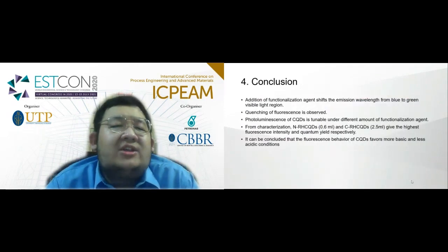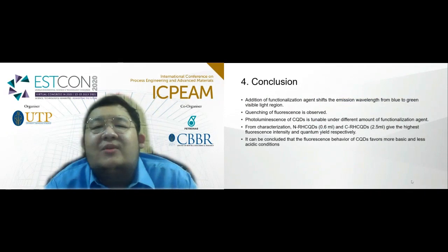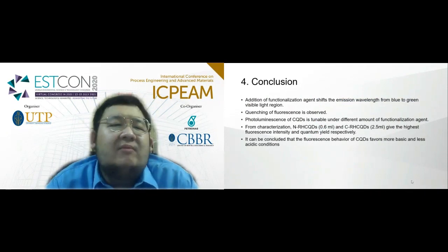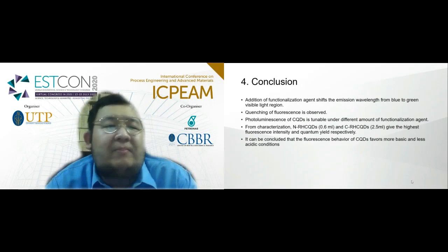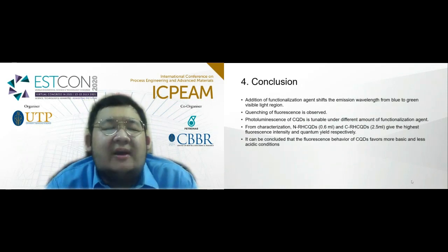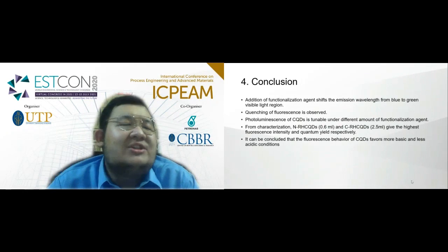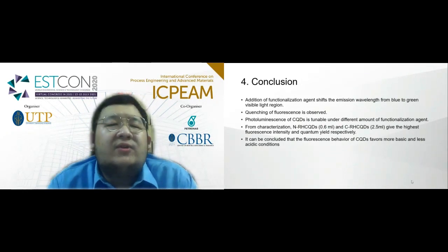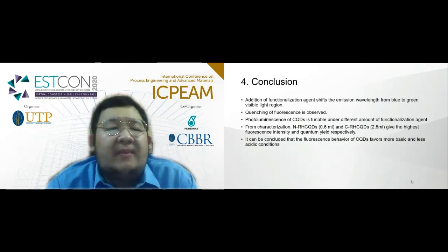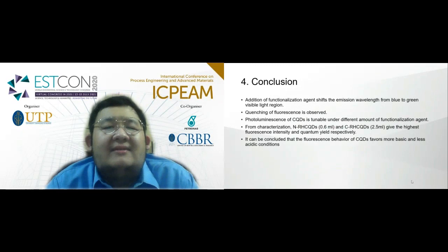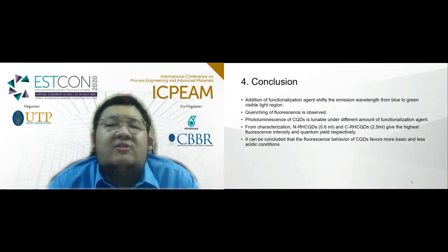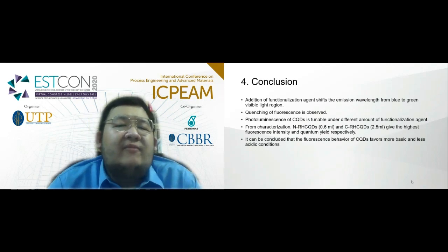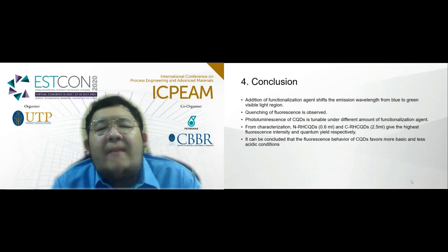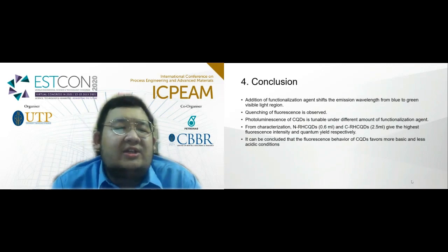In conclusion, the addition of functionalization agent shifts the emission wavelength from the blue to the green region, from 400 plus to 600 plus nanometers. Quenching of fluorescence is observed when we add the functionalization agent into the CQD. Photoluminescence of CQD is tunable under different amounts of functionalization agent. From the characterization itself, NCQD 0.6 ml and carboxyl CQD 2.5 ml give the best results. So it can be concluded that the fluorescence behavior of CQD favors a more basic and less acidic condition.